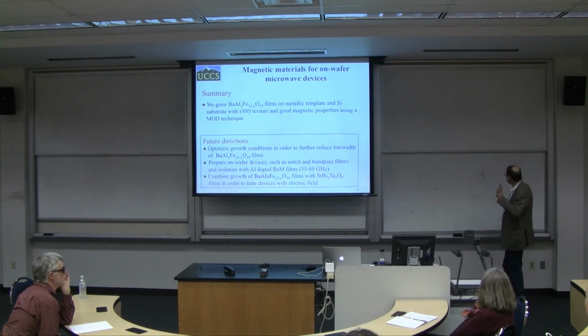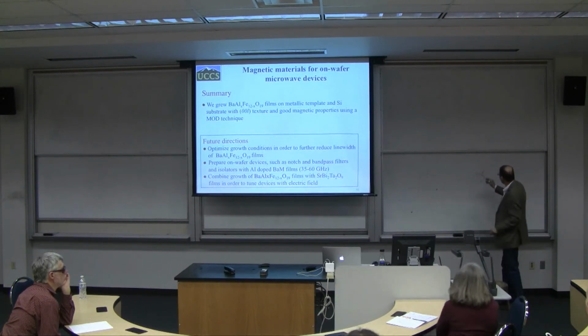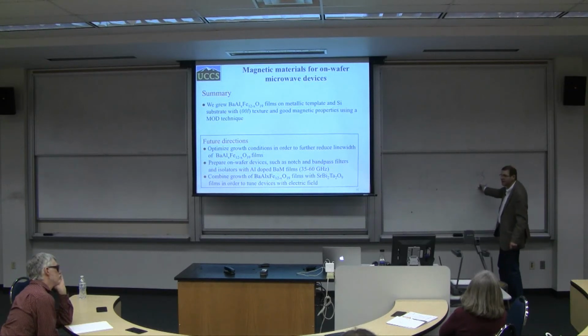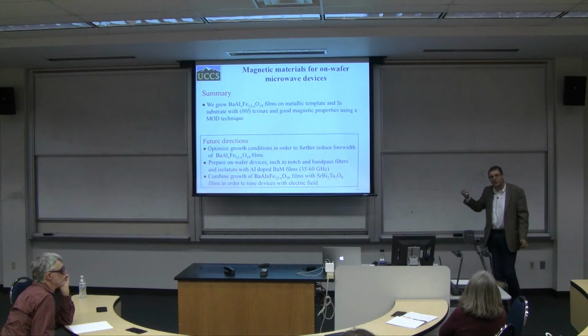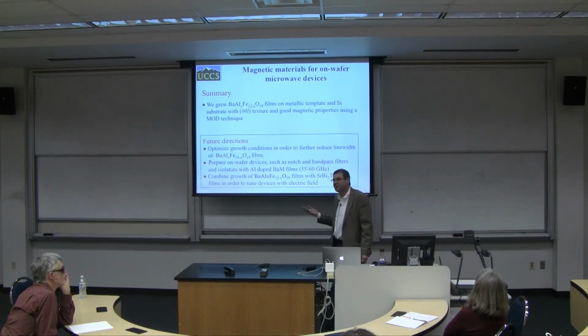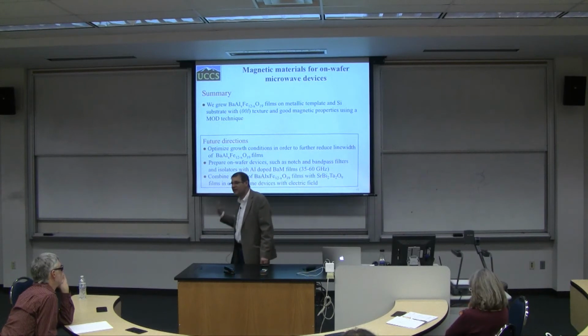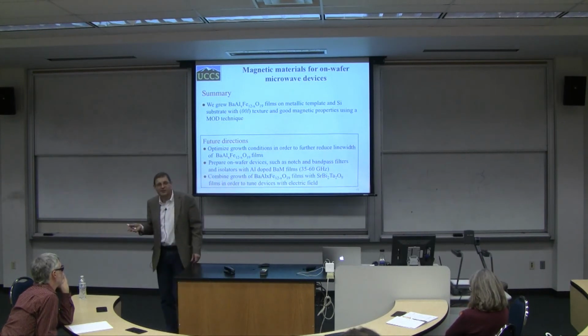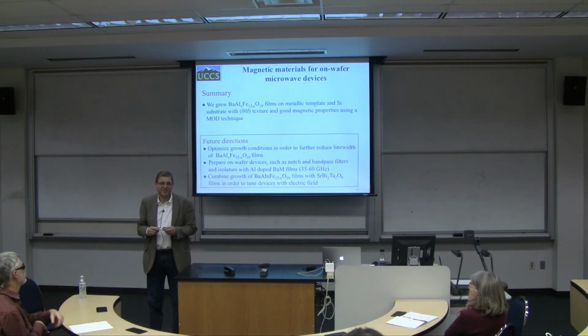So what's happened is the light goes in with the polarization like this, propagates through, and then in different areas, depending on the orientation of magnetization, the plane of polarization is slightly rotated or not. If it's rotated, you see this as a difference in intensity, and therefore you see dark and white. I mean, these changes are really minute.